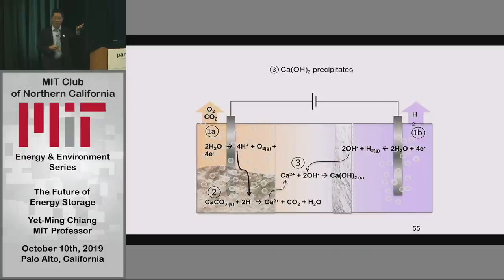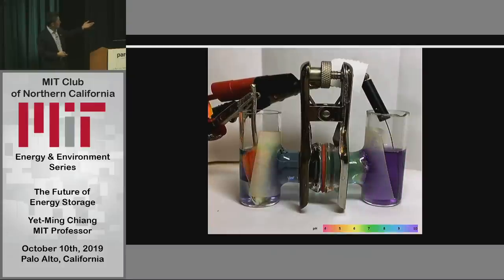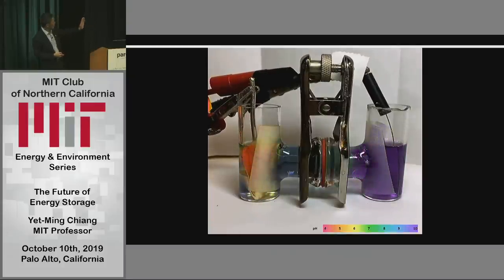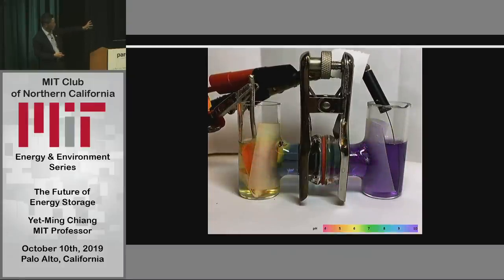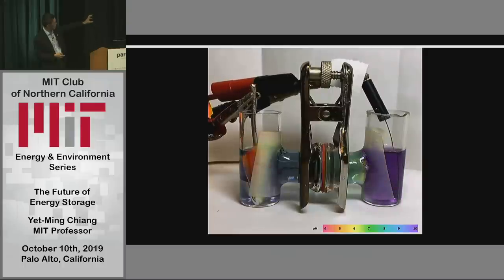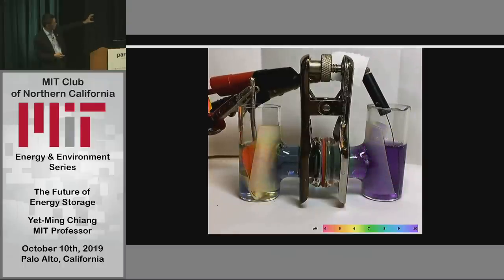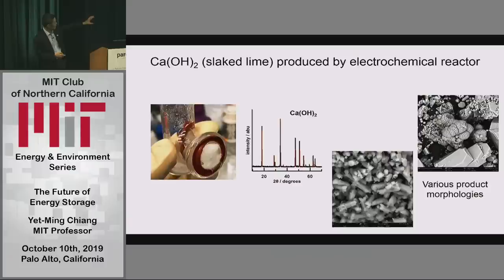So you imagine as this takes place, imagine a snow globe. And what's precipitating out is calcium hydroxide. Right? So this is what's going on in this case. And now there's calcium carbonate over here, a very simple reactor on a benchtop. And so you see that the yellow part is the middle pH. And so while that's taking place, we're precipitating calcium hydroxide. And it looks something like this white deposit you see on the left. Right? This calcium hydroxide